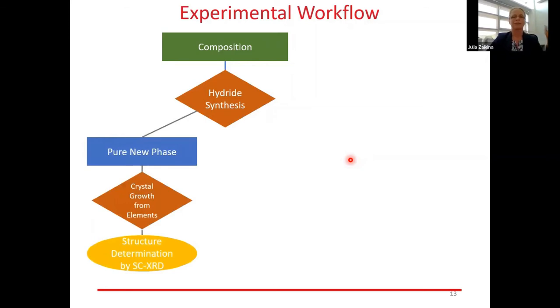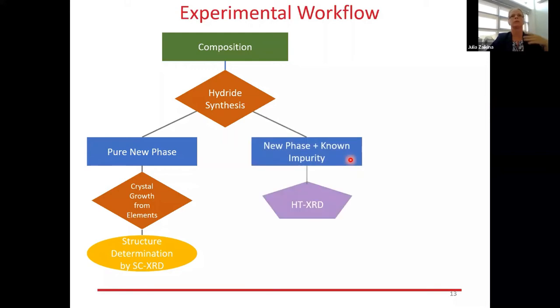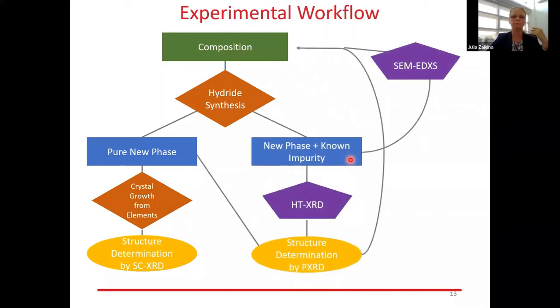If we're extremely lucky, we will produce a pure new phase, and then we can perform the crystal growth from elements to determine structure by single crystal X-ray diffraction. But oftentimes it's not the case, so we would produce a sample which may contain a new phase with a known impurity. So then the next question is, the composition was, let's say, pretty close. So what about the temperature? Yeah, so then we use high temperature X-ray diffraction to see at what temperature this new phase is stable. So then we can optimize our synthesis temperature and perform this cycle again.